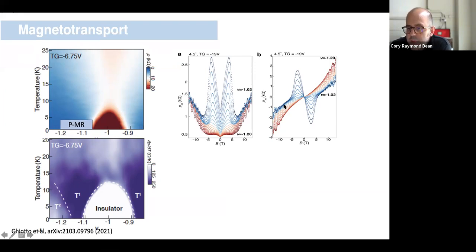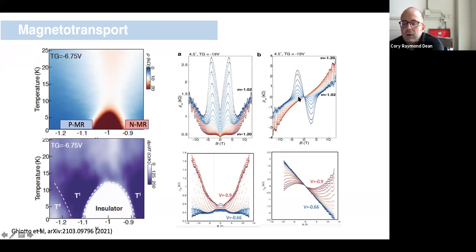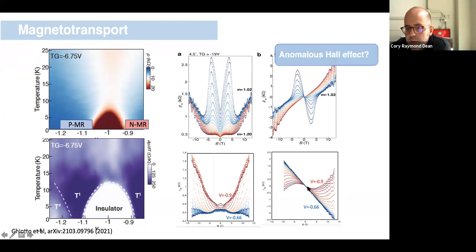The Hall resistance is even more strange. It shows a really massive increase in the Hall resistance as a function of B as we tune slightly away from zero B. If I go to the underdoped side, the curious thing is that the response is quite different. Initially, very close to the insulator, we see actually a negative magnetoresistance, which then beyond some threshold B transitions to a positive. And here the Hall resistance is much more well-behaved.